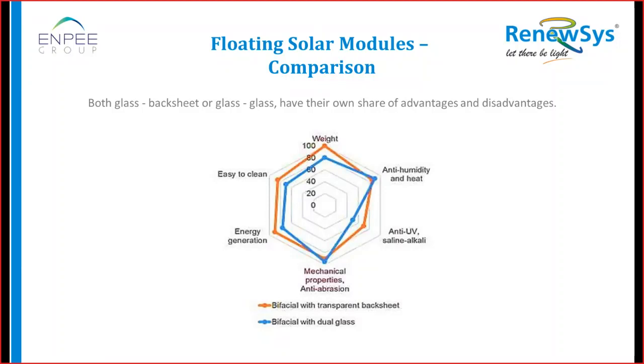So if you consider glass to glass and glass to backsheet, the key differentiator is the weight, where glass to backsheet has a very low weight, and it will give much stability, and it's easy to clean, because in glass to glass, if you have to clean, there is a chance of putting stress, and definitely glass tends to bow if there is no frame. And from an energy generation point of view, glass to backsheet is very clear because it has a slightly cooler effect than glass to glass. And glass to glass has certain advantages in mechanical properties, but generally it is not much needed for